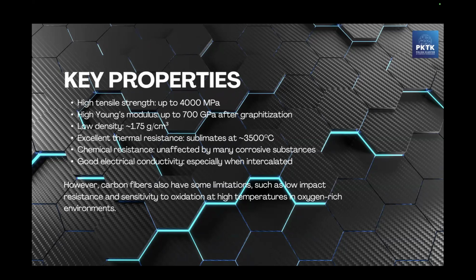This is up to 700 gigapascals, of course, after the graphitization. And of course, the graphitization process brings more cost to the production of carbon fibers. That's why carbon fibers are also expensive. Low density, this is 1.75 grams per cubic centimeter, and excellent thermal resistance.